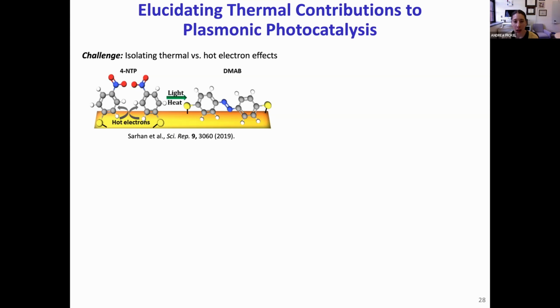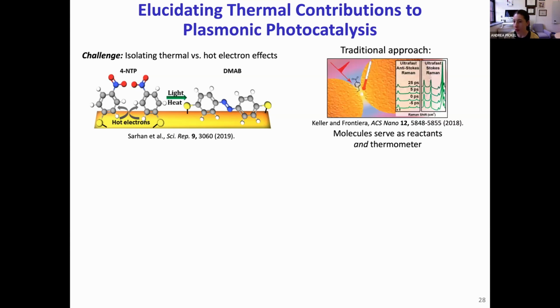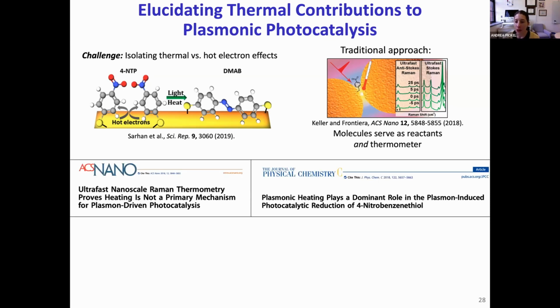And in particular, there's been an enormous amount of debate about the relative contributions of non-thermal hot electrons versus surface heating to the observed reaction enhancement. And so one way that people have tried to disentangle these effects is to not only use the Raman signals from the reacting molecules to monitor the chemical reaction, but also use anti-Stokes to Stokes Raman peak intensity ratios to measure temperature. And using this approach, different groups have studied the same chemical reactions, yet come to very different conclusions about the importance of heating for plasmonic photocatalysis.